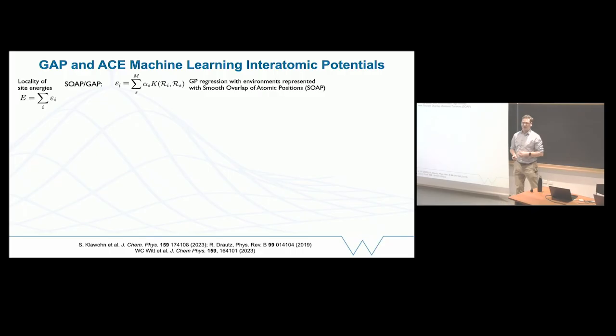So it's really easy to fit. It's a convex optimization problem. There's a formula to get the alpha, essentially. You don't have to optimize via gradient descent like you do with a neural network. It's also important to mention this M here is a user parameter. In the GAP framework, we call this the number of sparse points or inducing points. It doesn't have to equal all of your data set. So typically you might have 100,000, 200,000 atomic environments in your DFT database, but this sum doesn't have to go over that many points. It might be 1,000 or 2,000 or 10,000. It's something you choose. So you're effectively defining how big your basis needs to be in order to represent the variations that you see across your data set.